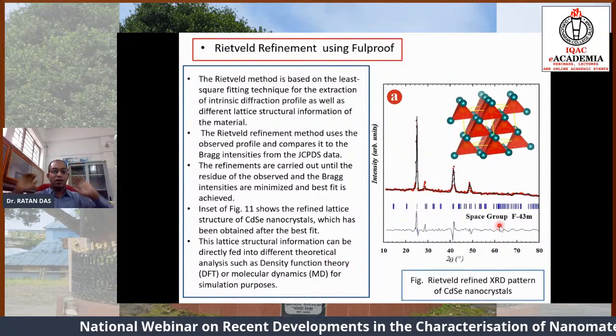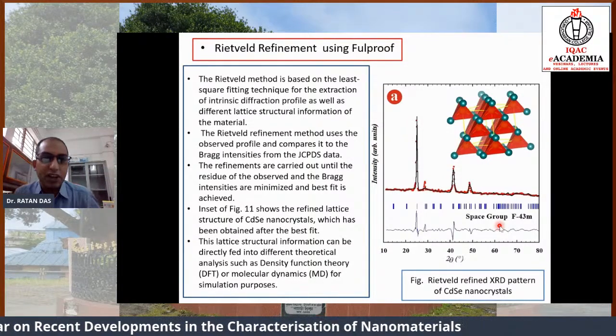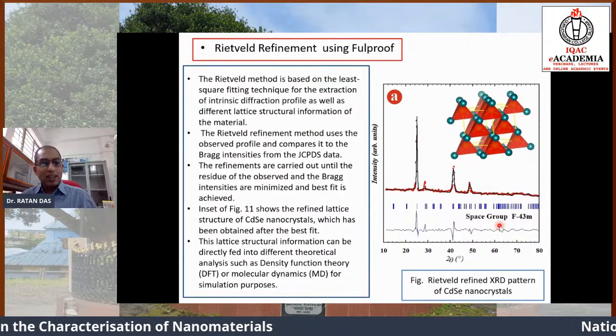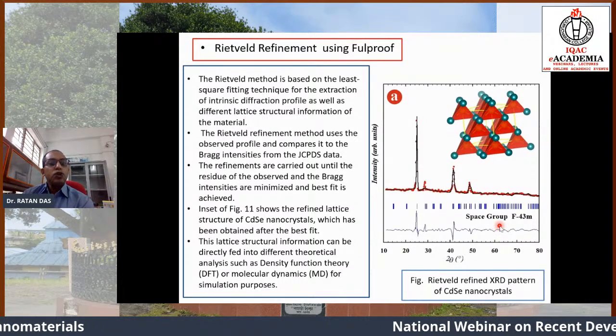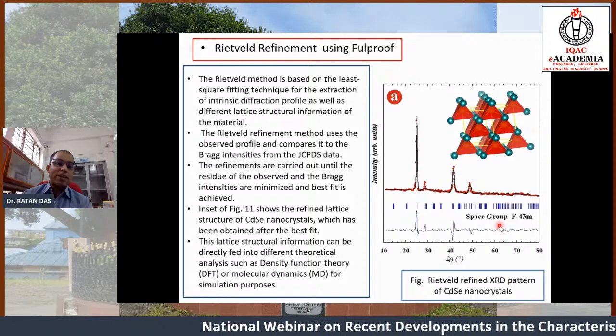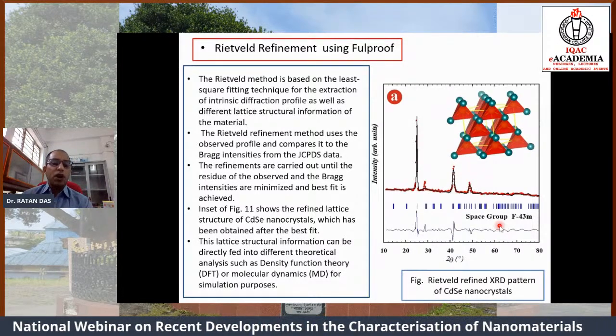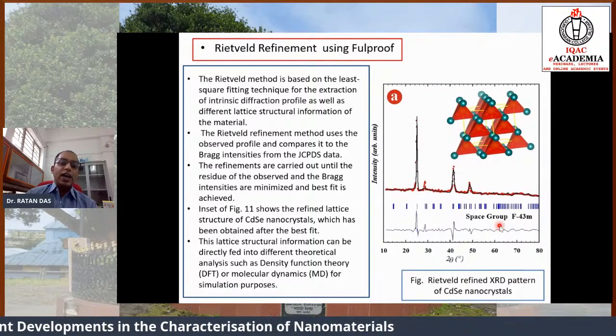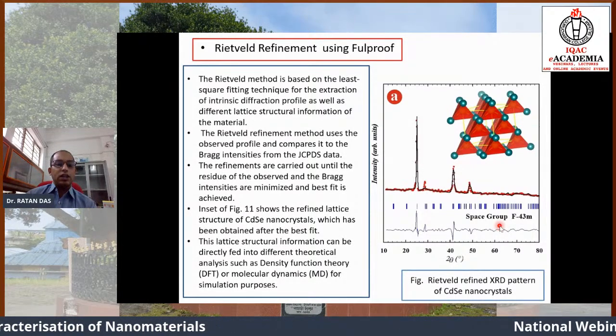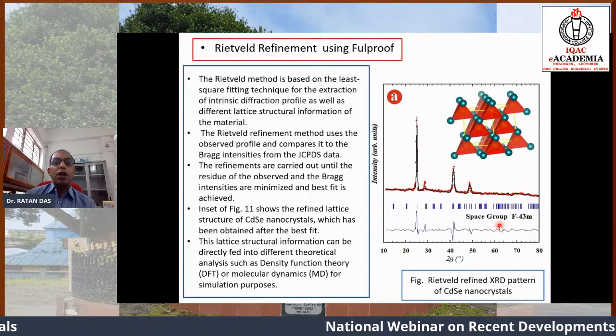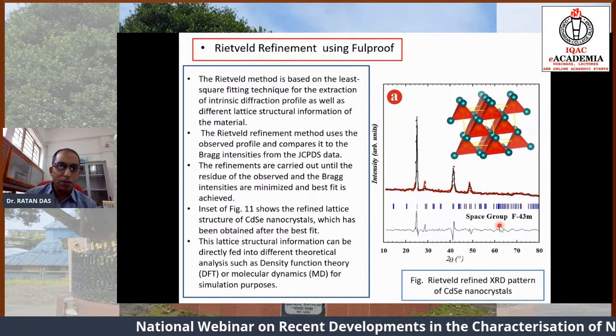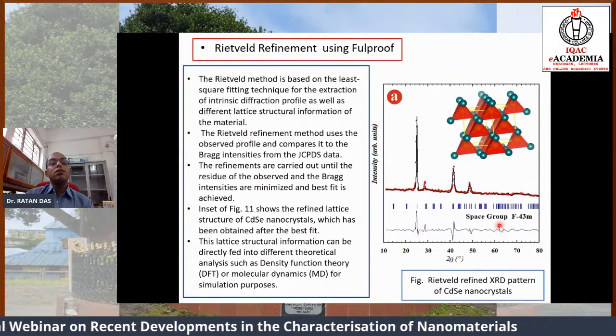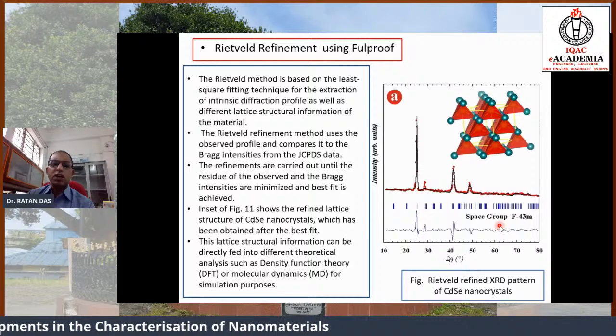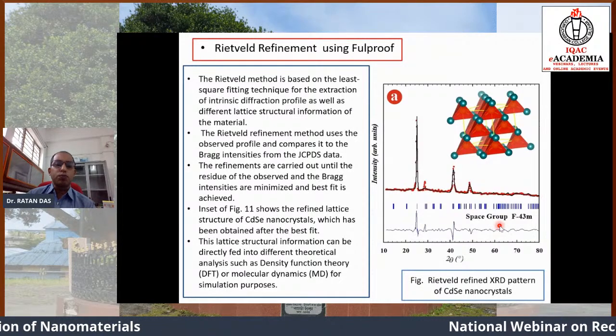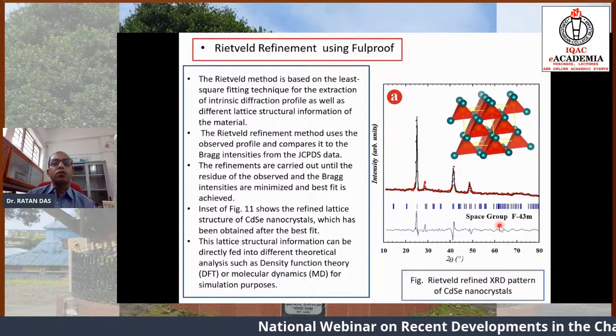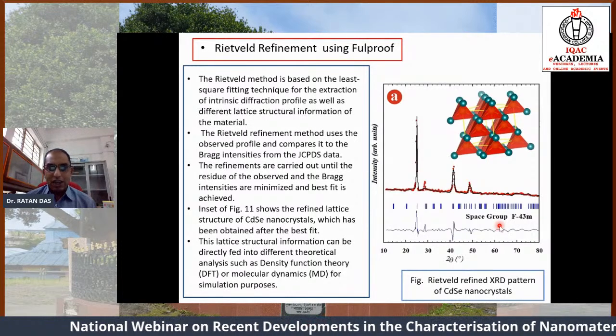Now, one of the important parts that I want to tell you is regarding the Rietveld refinement, which is very important in X-ray diffraction pattern analysis. I do not say it is complicated, but it needs lots of practice to get a hand in Rietveld refinement. We do the Rietveld refinement through a well-known software called FullProf, and using that software we do the refinement. What is the Rietveld refinement actually?